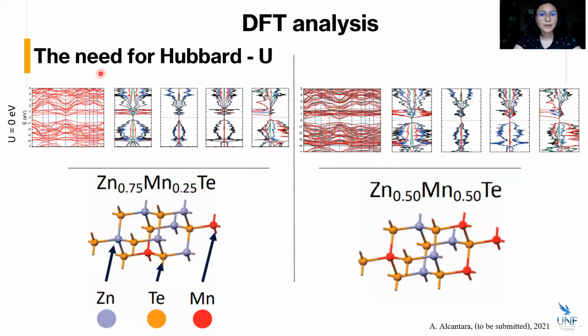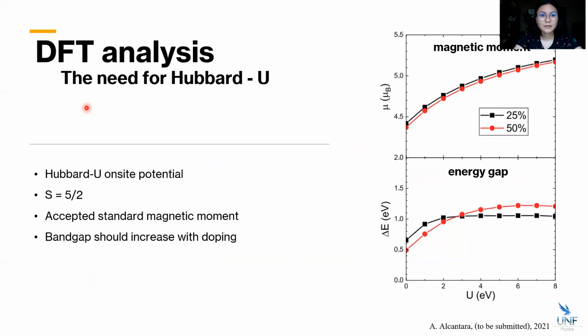So doping it with 25% and 50% manganese, you can see that there are impurity bands that start to show near the Fermi level, and they're really flat, and this is not what is expected from manganese. And so this is why we need a Hubbard U parameter, and what Hubbard U does is it's going to raise up these bands and provide more electron mobility for the system. So this is what happens when we apply Hubbard U.